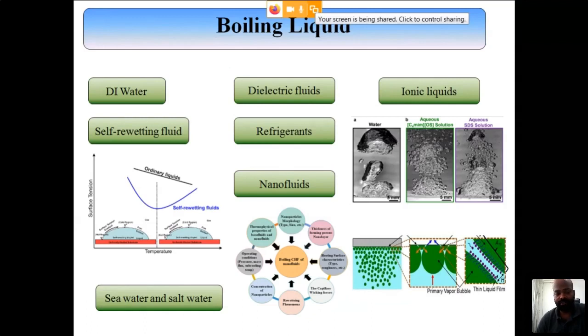This was a very interesting phenomenon, and it was used to improve the boiling. Because of this surface tension change, the liquid actually travels towards the surface at higher temperature. What we need during pool boiling heat transfer enhancement is, as the bubble moves away from the surface, the liquid surrounding it has to travel towards the surface, and it should wet the surface for the next possible generation of bubble. At higher heat fluxes this does not happen. You have so many continuous bubbles that the liquid cannot come and touch the surface. But when used with these fluids, the performance was found to be improved, but this has got some safety issues associated with it.